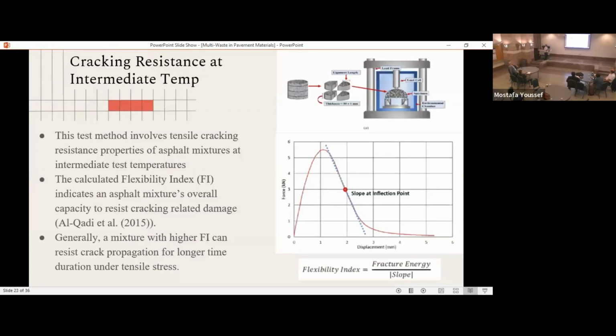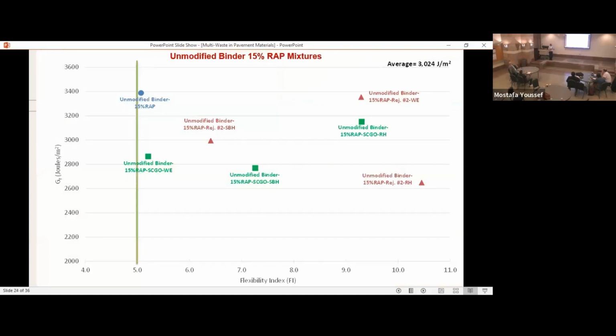And again, building from there, focusing on damage properties, continuing with the same theme as I talked about before. Looking at the semicircular beam test, SCB, you create a sample with a notch, so you control the crack, and you apply simple bending at room temperature. What you measure out of it is not only the fracture energy, but the flexibility index, which is the ratio between the fracture energy and the slope of crack propagation. So that is the energy required to initiate the crack, and the crack propagation rate. The higher that ratio, the more flexible the material.